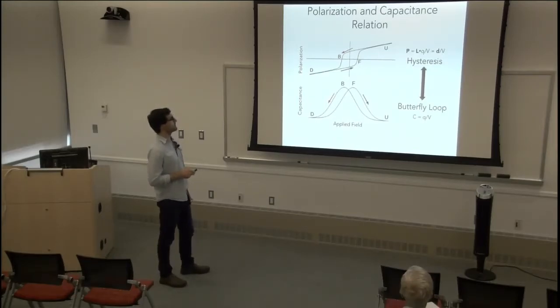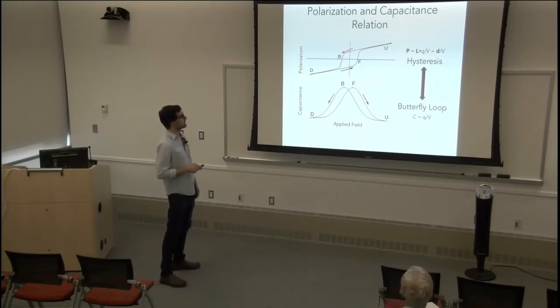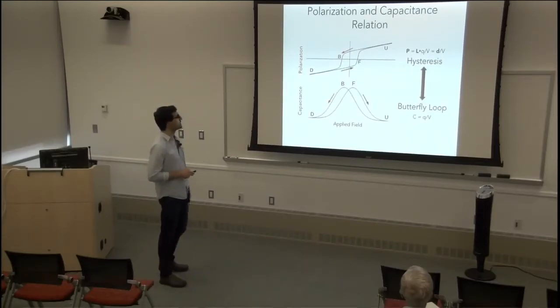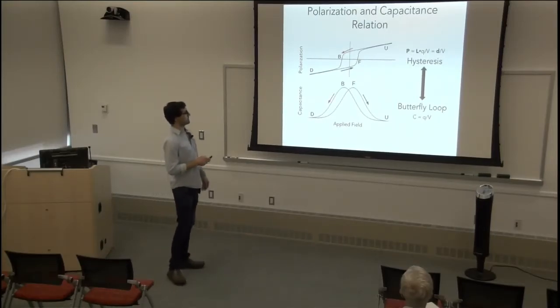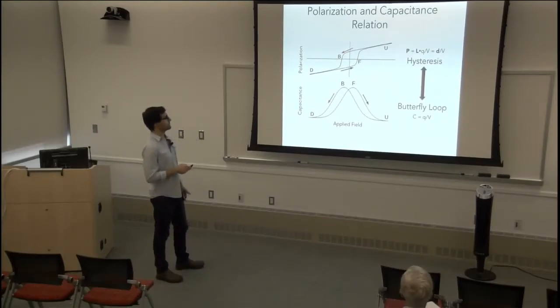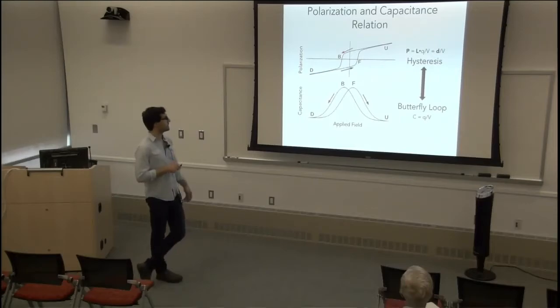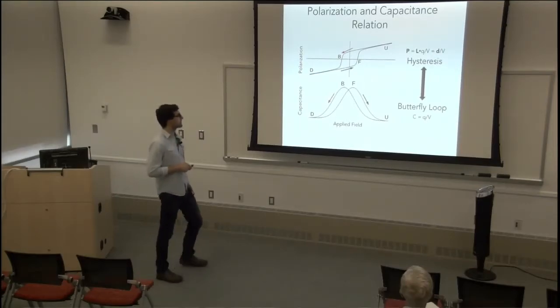Well, it turns out that there's an equally similar measurement you can do to get more or less the same type of information. It's called a butterfly loop. Instead of measuring polarization, which is dipole moment per volume, a butterfly loop measures capacitance, which is charge per voltage. While the figures look quite different, they're related in some nonlinear way. There's a nonlinear mapping where you can go from capacitance to polarization and polarization back to capacitance.